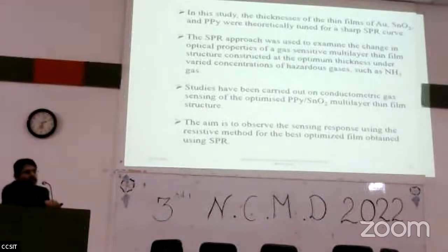So again, we optimized theoretically the thickness of gold, tin oxide and polypyrrole thickness. Then observe their reflectance curve, and we also perform the conductometric studies. So this is the obtained result. As we can see, resonance angle increases, and reflectance decreases when we vary the thickness of the metal semiconductor. This is separately plotted, and again we obtain the full width at half maximum at the optimized thickness of 100 nanometers.